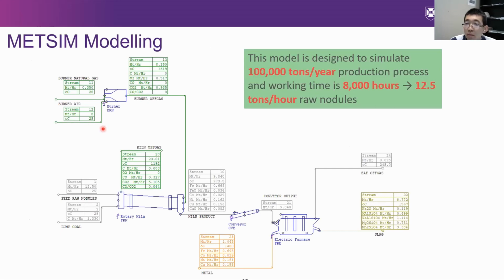We made a design to simulate a 100,000 tons per year production process to treat the nodules. In the rotary kiln, we simulate the temperature at around 1000 degrees, and then without flux addition, the electric furnace is at around 1550 degrees. The ferroalloys were reduced with around 70% iron, 3% cobalt, and around 15% nickel and copper.